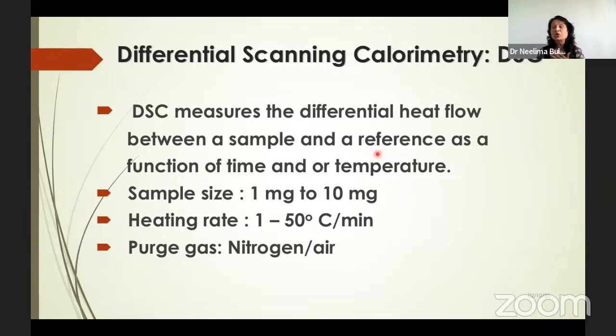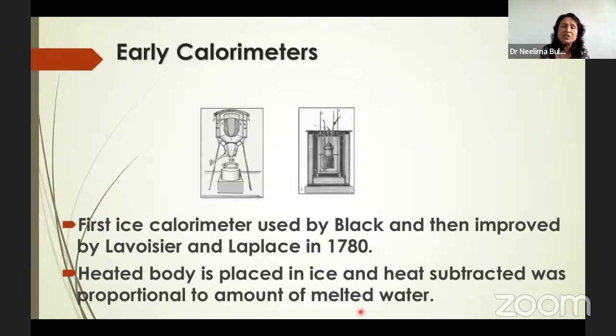It gives us the first or second order transitions of the material. Sample size is 1 mg to 10 mg. Heating rate can vary from 1 to 50 degrees, and the atmosphere can be nitrogen or air. It's a pretty old technique. The first calorimeter was used by Black, and it was improved by Lavoisier and Laplace in 1780.